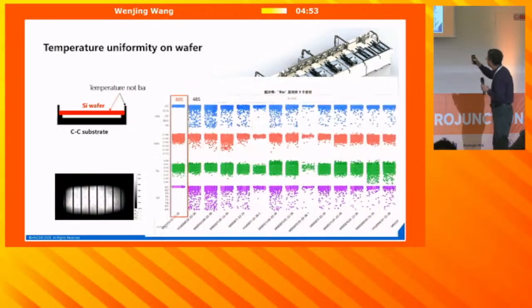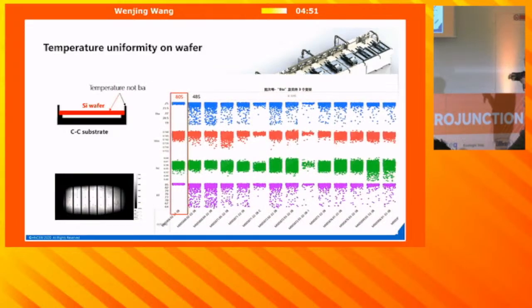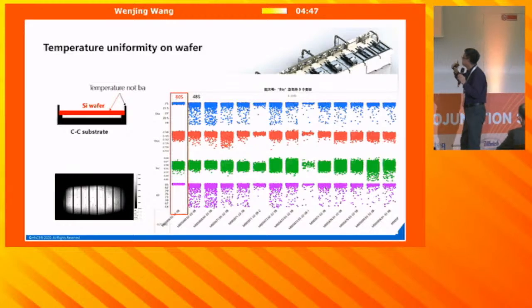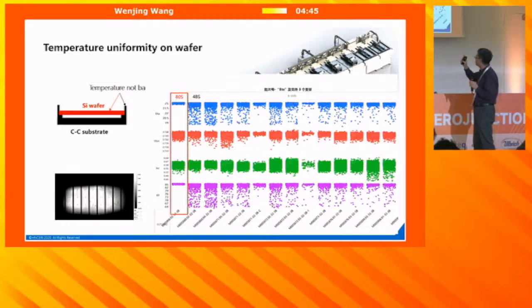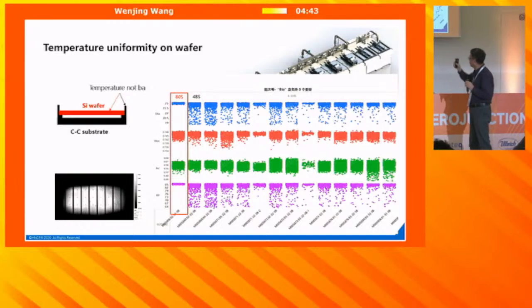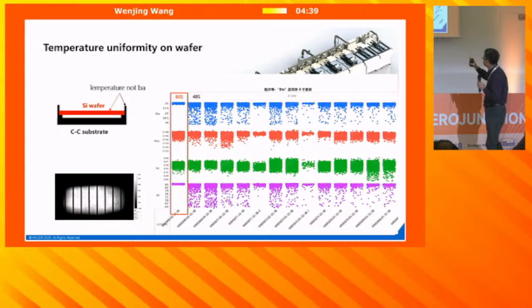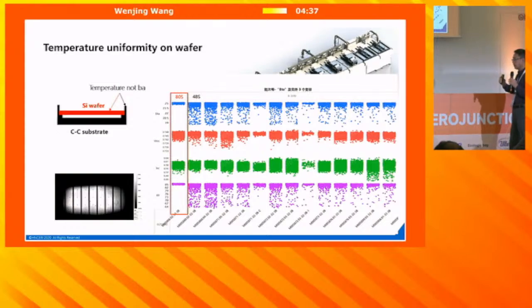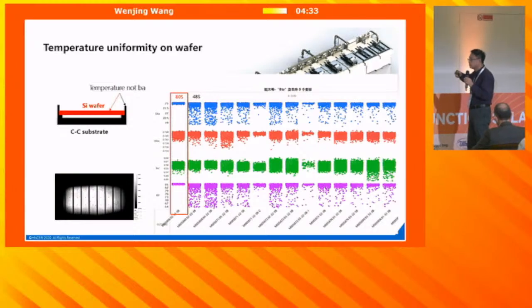So for our PECVD tools, if we use a decay time of 80 seconds, the distribution is quite good and the efficiency is high. But if you use a shorter decay time, you can hurry up, but maybe the efficiency becomes lower and the distribution becomes wider.